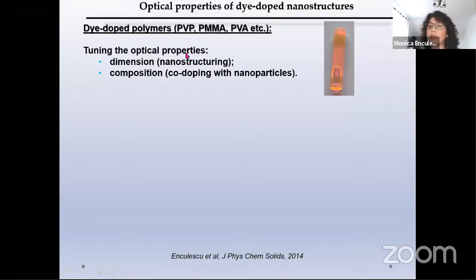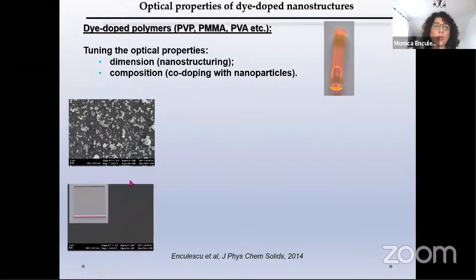We can tune the optical properties of these fibers, because there are two possibilities in which we can tune the optical properties. We can play with the dimension. We can structure this type of fibers further, or we can play with the composition, put some co-doping into this type of fibers. So we can change from thin films of this type of polymer that are doped with dyes. We can electrospray them.